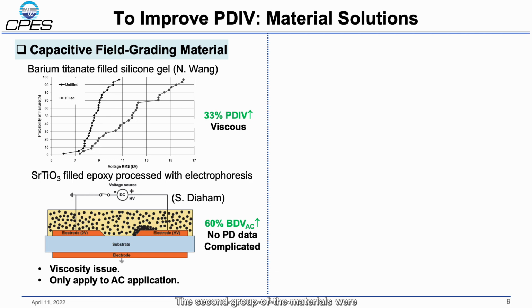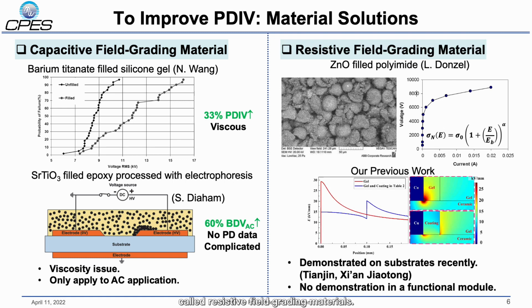The second group of the materials were called resistive field grading materials. Zinc oxide and silicon carbide were usually used to fill into the polymer matrix. As shown in this curve, they are more insulative under low electric field but more resistive under high electric field. We proposed to use this kind of material as a coating or shielding layer at the critical regions in the power module prior to the primary insulation, for example, silicon gel.